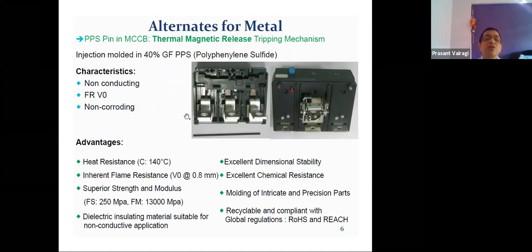Considering the heat resistance in this region, and other aspects that we have discussed, this is the base material and it is working smoothly. After introducing this, we have forgotten about any customer complaints and those kinds of issues. The material has excellent dimensional stability, excellent chemical resistance, and from the molding point of view, how precisely you can mold it. And obviously, the moment it is thermoplastic, recyclability and compliance with RoHS and REACH is intact. So this is the advantage that one can get.